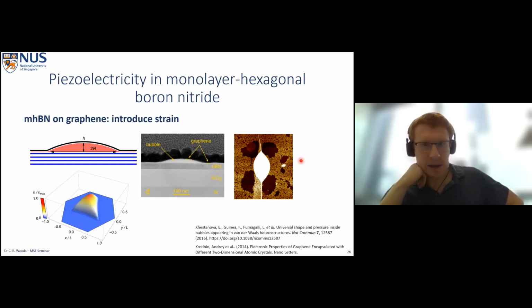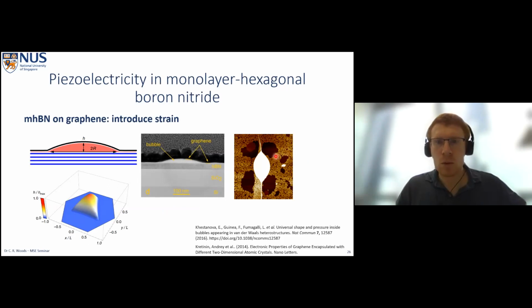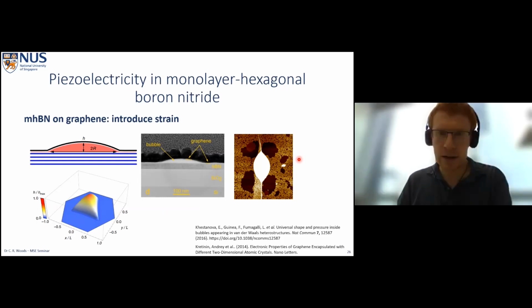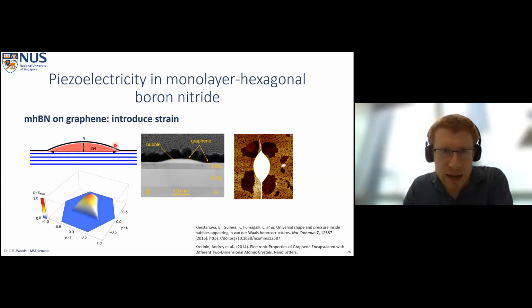So we can talk about these bubbles a little bit more. Quite a lot of work has been done on understanding them, on understanding the strain in the layers that make them, and how it's related to the adhesion between the two layers which produce them. And they actually contain a huge amount of pressure, so up to gigapascals within the actual bubble themselves. And as you'd expect with gigapascals, we get a lot of strain on the surface here, but we also get a lot of strain propagating out into our heterostructure radially. And it dissipates slowly, in say several hundred nanometers, as we move away from the edge of the bubble.